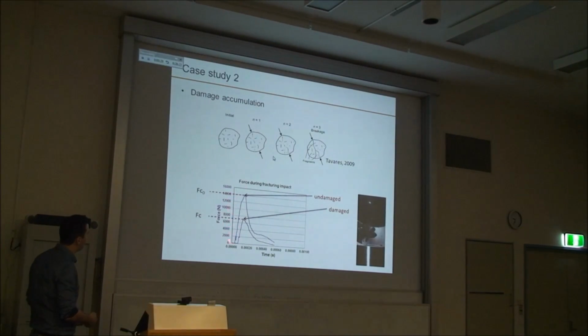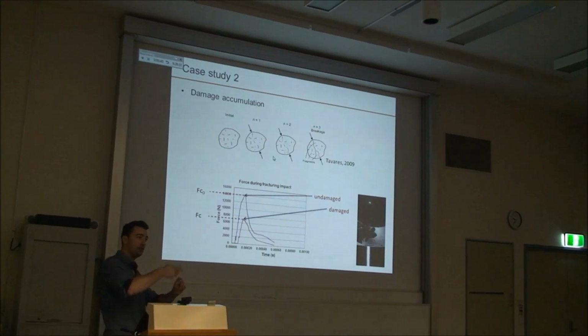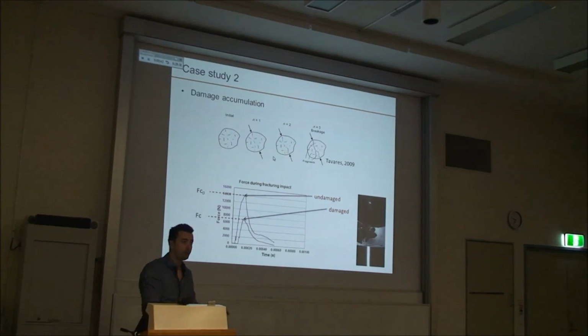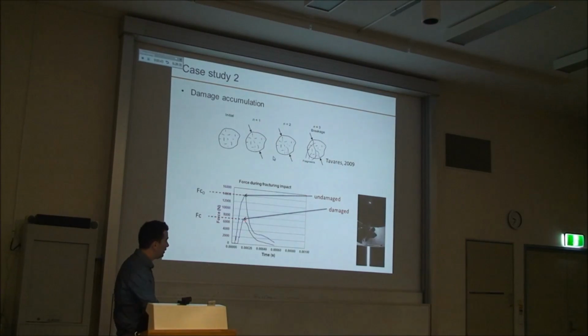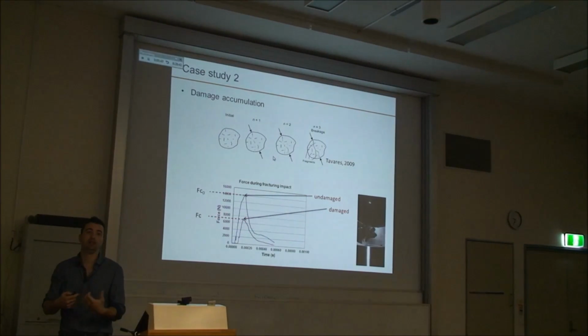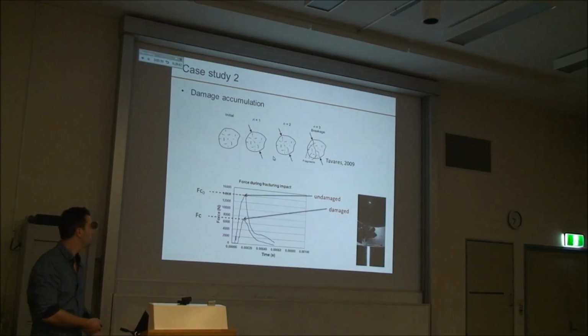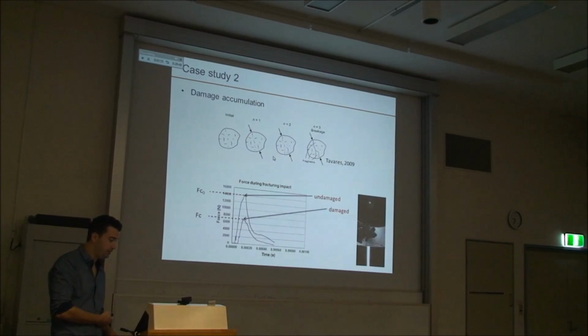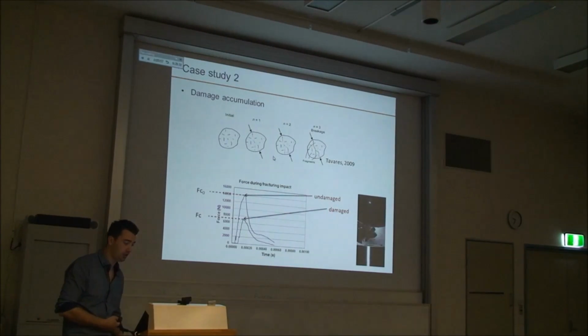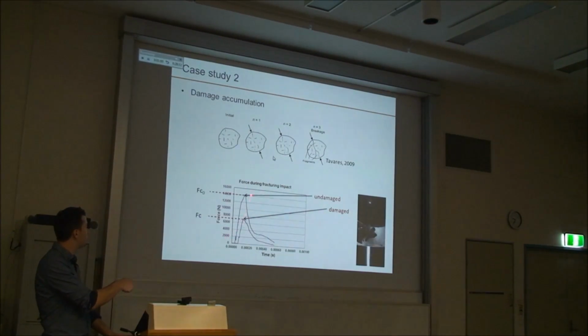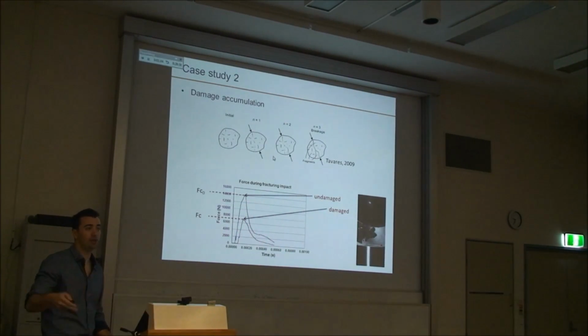And this is the fracture force obtained for an intact cube, so a cube that was not damaged. And here, it's a damaged cube that was impacted 20 times. So with the same cube, we've impacted it without breaking it. And this is the fracture force. So there is a clear relationship between the damage that was accumulated in the rock and the fracture force. So again, another application for the impact load cell to assess the damage accumulation. By the way, there's a model to predict the reduction in strength and in fracture force, depending on the number of impacts you've applied.